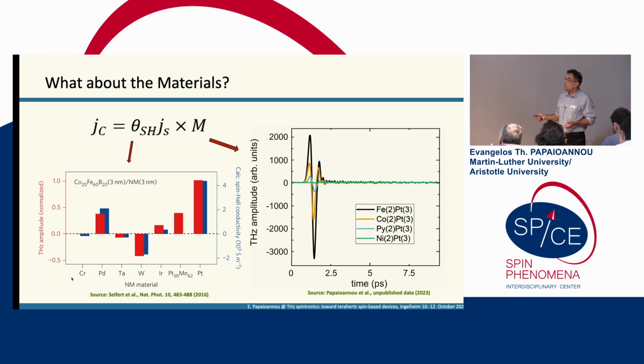And also concerning the magnets, so the magnetic layers, here is data from our lab. You see iron, compare here iron 2, platinum 3, all the same thicknesses. Iron is also the strongest one, followed by cobalt, and nickel is the lowest one, but now this has also another perspective concerning the orbital moments. So this is known.